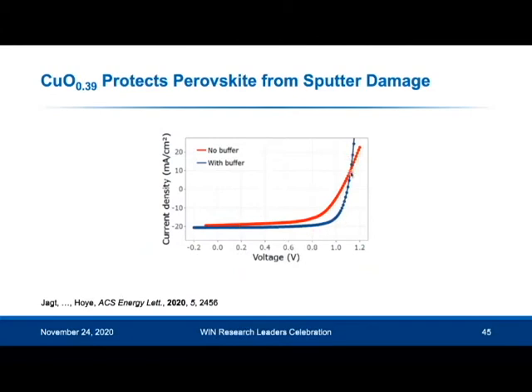And you can see that having a cuprous oxide buffer layer is sufficient for protecting the perovskite from sputter damage and allowing us to have a good fill factor with a decent efficiency of 16.7% for semi-transparent devices, and that's comparable to the state-of-the-art for semi-transparent perovskite top cells.